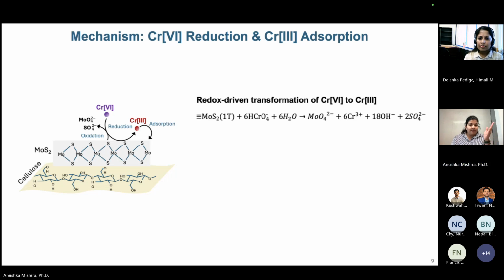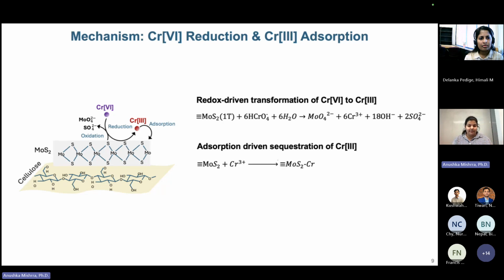So with that, we went ahead and looked at the reactions carefully. We know that there is redox happening where the chromium-6 is going to chromium-3 through MoS2, and you can see that in this process, it's consuming protons and creating hydroxyl ions.